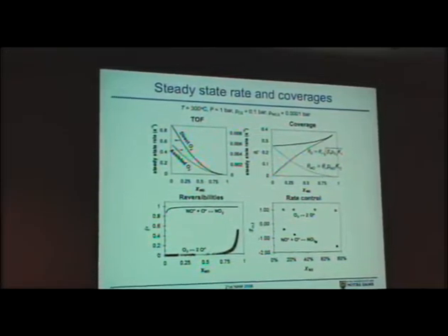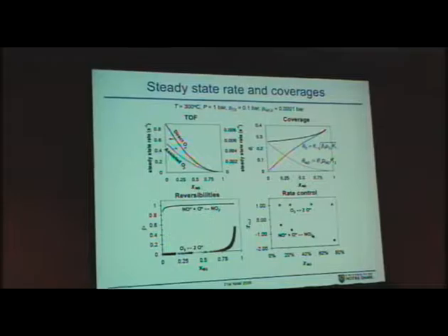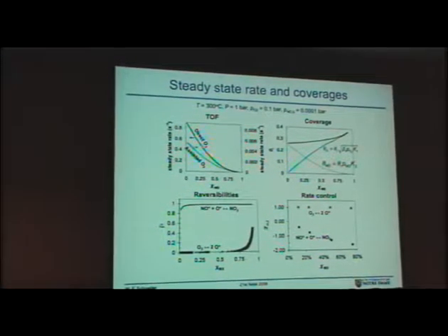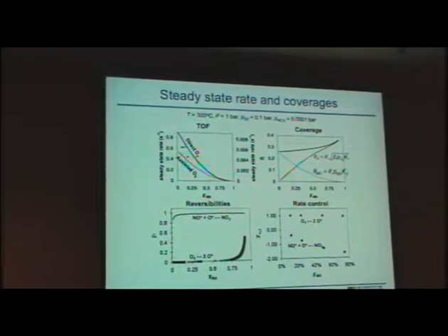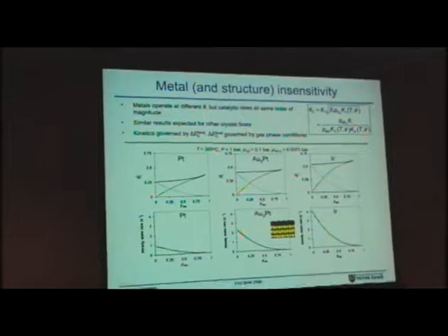So this reaction is controlling the oxygen coverage. This reaction is rapid at all conditions. O2 dissociation is rate limited, and that's also verified by looking at the degree of rate control. All right, so that's great.